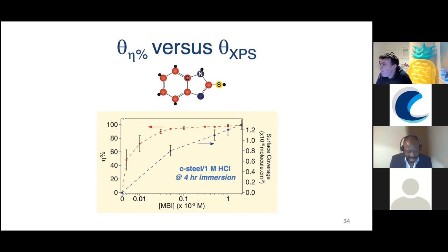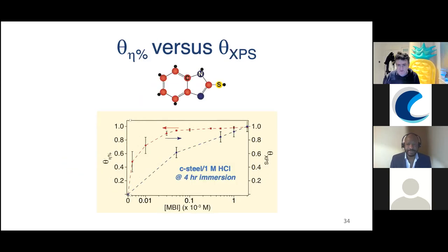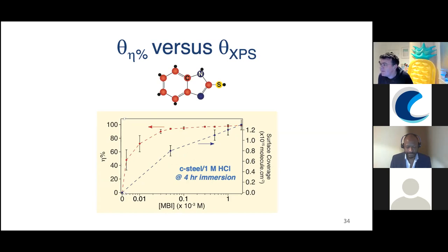Okay, next we have: for sulfuric acid, does the inhibitor help build up the iron sulfate layer? And does the inhibitor bond with the sulfate layer or the underlying metal in gaps within the sulfate layer? So we think the iron sulfate layer will be there. I didn't show you uninhibited because we haven't done so much work on that, but we think the iron sulfate layer will be there even if it's uninhibited.